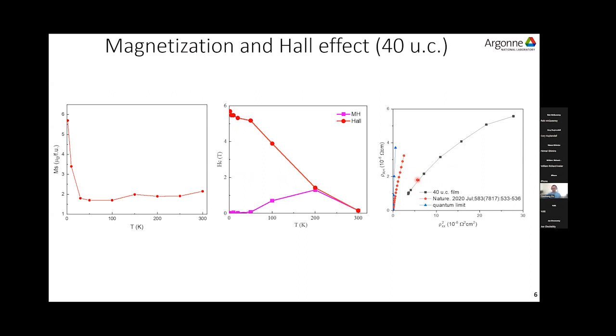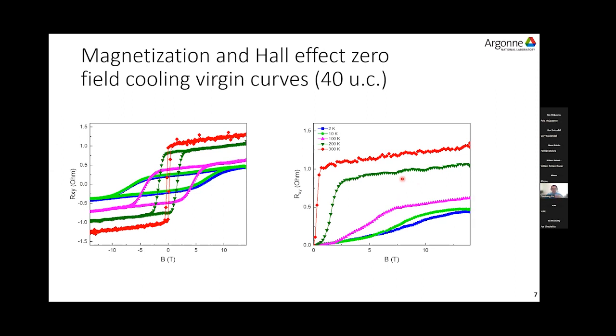So we have moved to the next step to check the possible magnetic structure in the thin film. In order to check what really happened in the thin film, other than the hysteresis loop, we measured the zero field cooling Hall and magnetization curves at even higher fields. The Hall loops for the 14 Tesla measurement are the same as the 9 Tesla measurement. If we look at the virgin Hall curves, we have some interesting facts. The first is at low temperature, here at 2 and 10 Kelvin, it has no remnant at low fields, and then starts to saturate above 7 Tesla. But if we increase the temperature, they start to show anomalous Hall effect.